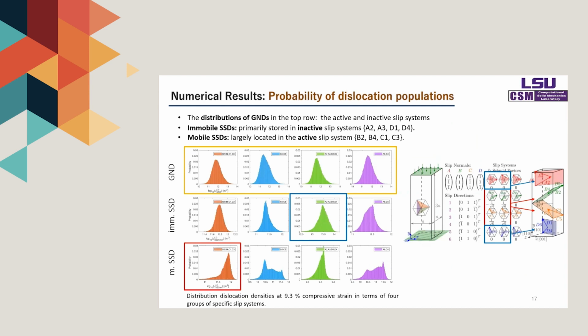To determine the internal distribution of dislocation densities, the slip system of each dislocation density were classified into 4 groups. The figures for Model 1 describe the probability of GNDs, mobile SSDs, and immobile SSDs based on the 4 groups that you see here.